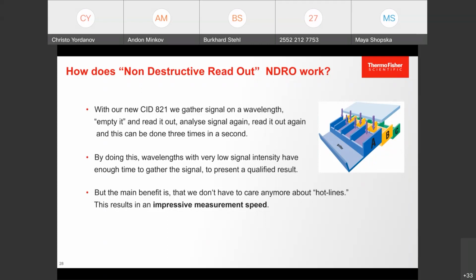With our new non-destructive readout, every pixel reads out 3 times a second and empties again. So it can collect calcium, calcium, calcium, until we have the full calcium signal, and also the very weak arsenic peak can be gathered. So we can measure with this new detector one element very high and the other very low, nearby the detection limit. That's a real advantage, also for cost saving and work saving. This high density of elements in a line is called a so-called hot line.